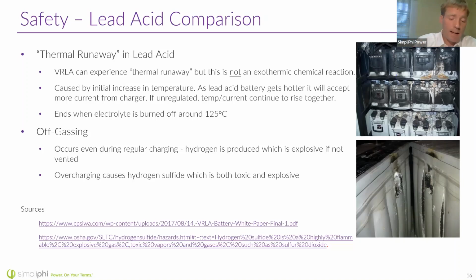What happens inside a lead acid battery is you have an aqueous solution, which means a water-based solution. So you have a sulfuric acid inside lead acid batteries. If you get them too hot, now this says 125 Celsius on here, but really the sulfuric acid will start boiling at a lower temperature than that.